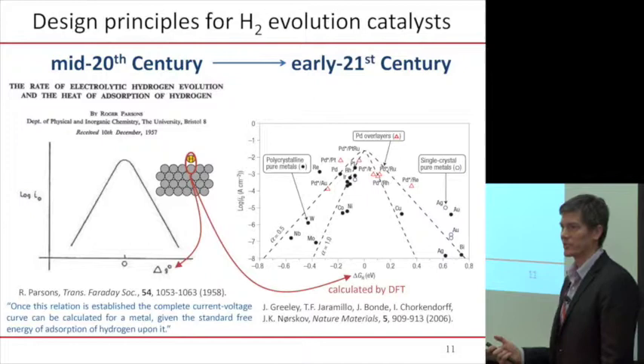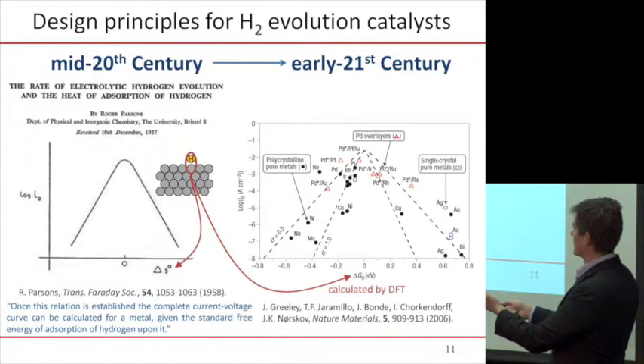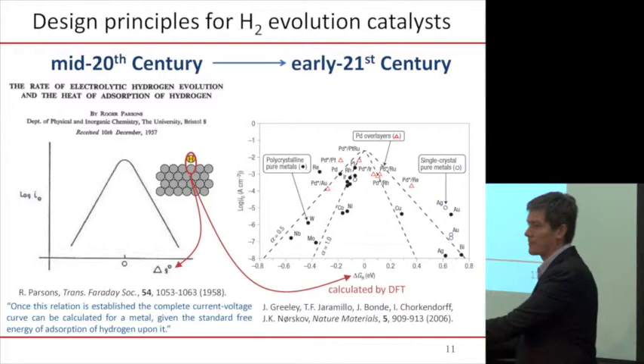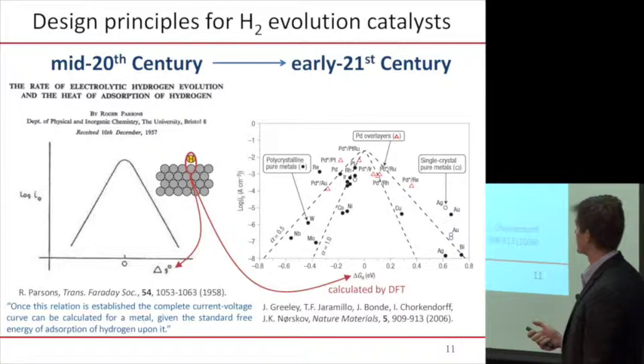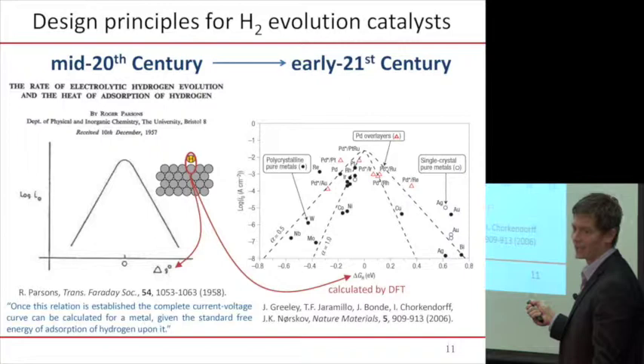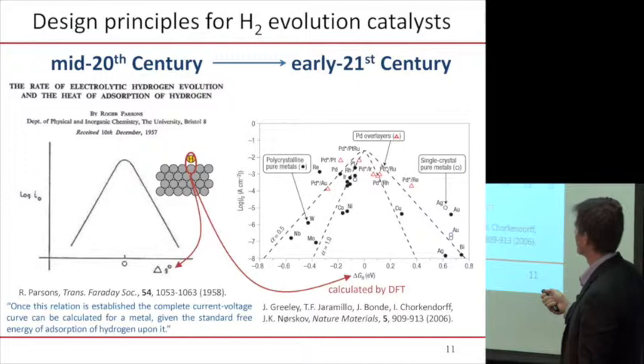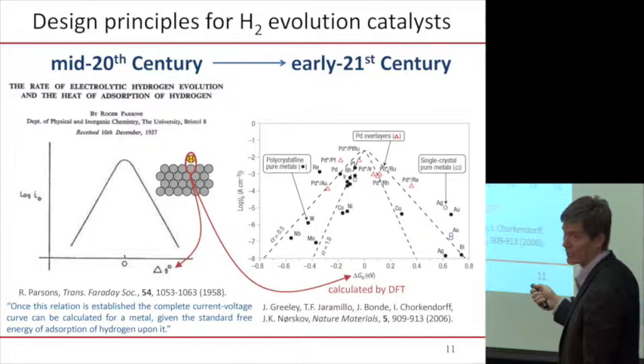But the issue at this time was, how do you know what the delta G is for this process? It would actually take more time to figure that out than just measuring the thing for hydrogen in the first place. But now you advance 50 plus years, and now we can use computers to do that. So with density functional theory, we can actually calculate that delta G of hydrogen adsorption. You can see that this is all experimental data on the y-axis plotted versus calculated values on the x-axis, and you get exactly this volcano-type relationship. So it gives you a sense that we understand what the problems are in this reaction.